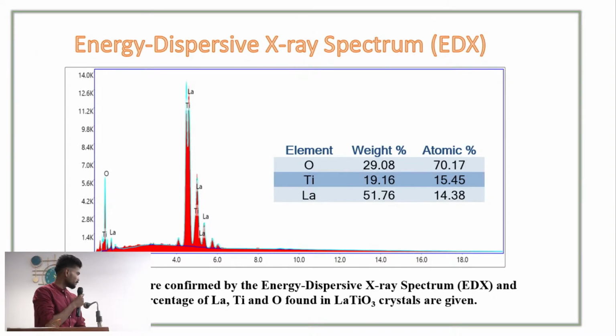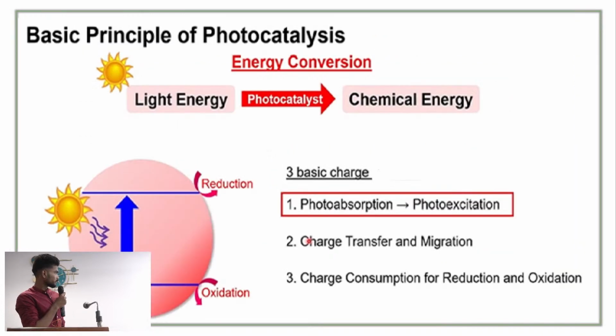In the EDAX, the sample is confirmed by the energy dispersive X-ray spectrum, and the weight percentage of the lanthanum titanate crystal is given, where oxygen has a large atomic percentage compared to lanthanum and titanium, which are in a molar ratio of 1:1:3.